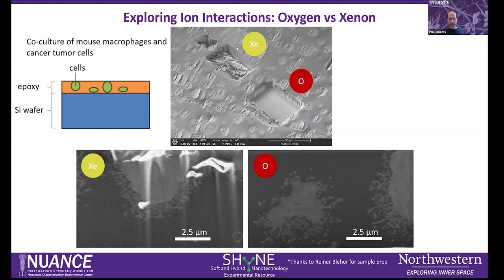If we then dive into the cross section and image it, you can see that xenon here creates more artifacts in the cut - these streaks are so-called curtaining artifacts - whereas oxygen really provides a nice smooth cut for these types of materials.